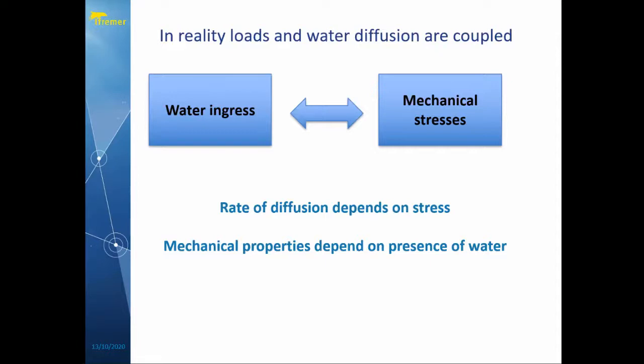And the mechanical properties depend on the amount of water in the material. So they're tending to degrade, and as they degrade, you also get damage introduced, which can also accelerate water ingress, and at some point you can reach an auto-accelerated degradation. Just to give an example of how the water ingress affects the damage and how this can then affect the water ingress, on the next slide.